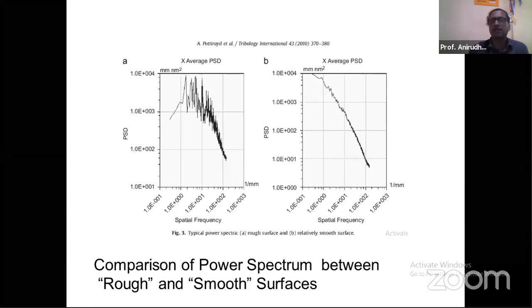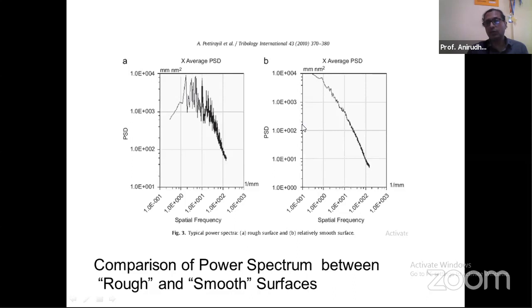The area under this power spectrum is a measure of this RQ value. So we can use RQ value because it is a more common descriptor. And we used another parameter which is related to the frequency of packing, which we found as the centroidal frequency, or some kind of a representative frequency, which is a mean frequency or a centroidal frequency belonging to this spectrum. When you compare that mean frequency in these two cases, you will see that it is more towards the right for the rougher one, while in this case it is closer to the left hand one because it is falling down. There is hardly any contribution from what is happening on the right because it is falling off.